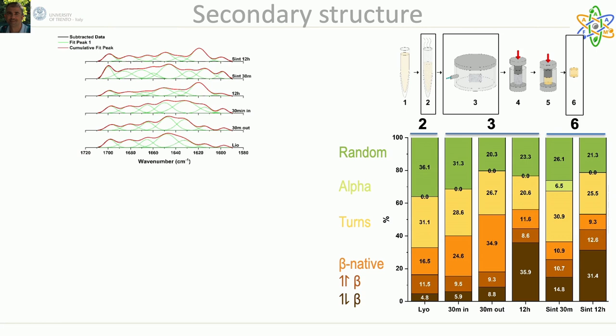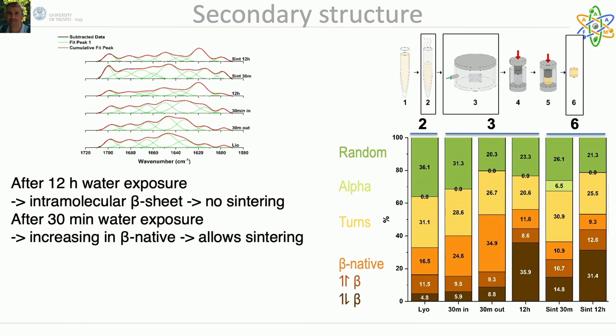We decided to compare the transition after sintering of dry flakes and hydrated flakes for a short time, 30 minutes, and a long time, 12 hours. We analyzed just after lyophilization. When analyzed just after lyophilization, the flakes appeared to have very low crystallinity levels, with very low levels of antiparallel and stable beta sheets, which rise from about 5 to 9% when exposed to water vapor for 30 minutes.